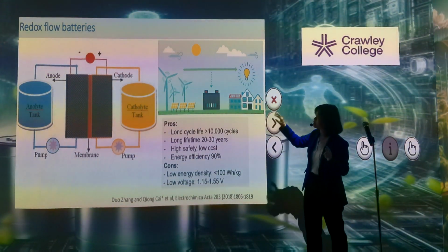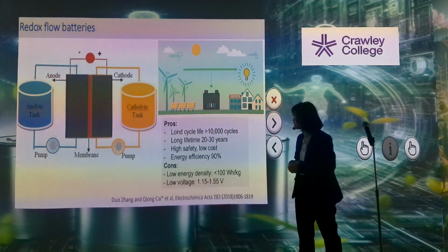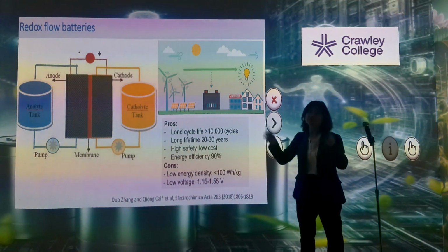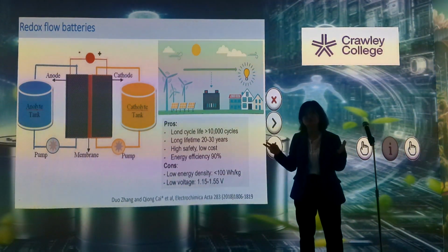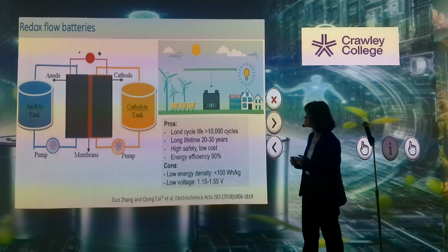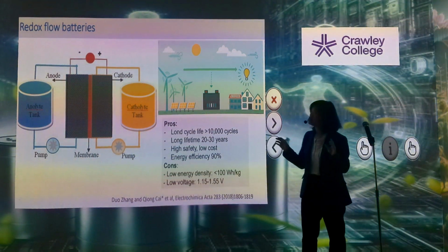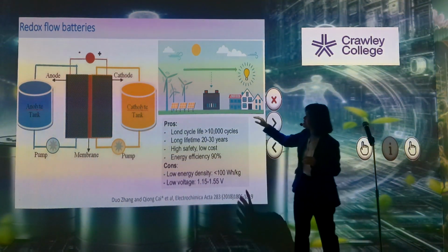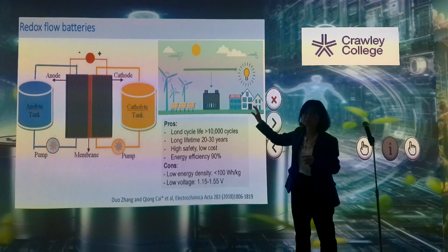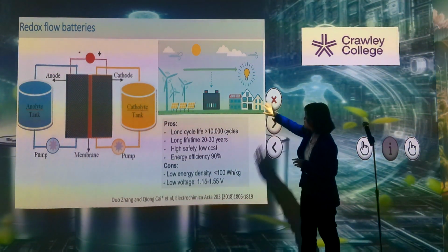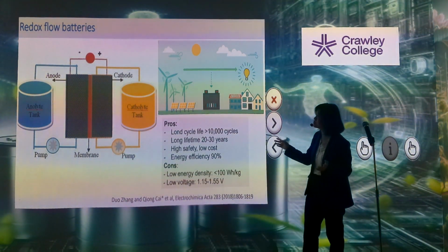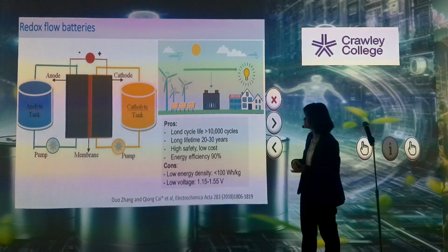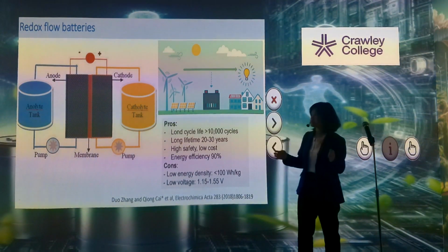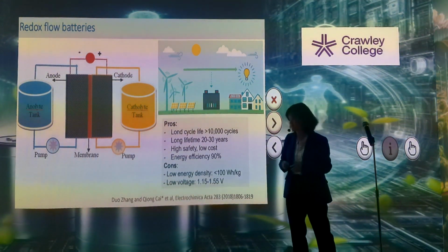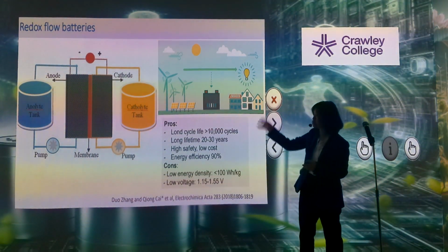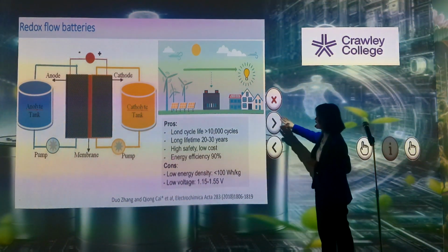The good thing about this type of battery is they have long cycle life, typically reaching 10,000 cycles, where the typical cycle life for a lithium-ion battery is probably 3,000 cycles. And then the long lifetime, probably 20 to 30 years. This is what we would like to have for grid energy storage, to store energy from renewable solar and wind, and then supply domestic or industry applications. Also, because they don't involve organic solvents, they have high safety and low cost. The disadvantage of this type of battery is they have much lower energy density and low voltage, because typically they use aqueous electrolyte. With water, you cannot reach very high voltage.